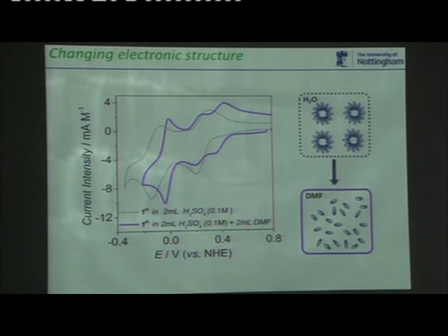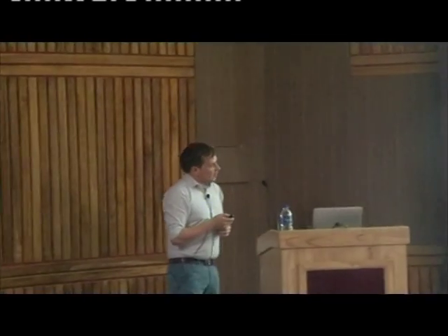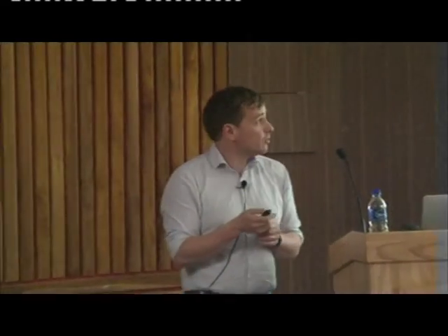And what this means is that these POM aggregates are having a major influence. The electronic structure is changing through the formation of the aggregates, and we think it's through Coulombic repulsion, i.e. when we have the micelles, it's more difficult to add electrons to them through repulsions. So we're having a look, and we'll try to get to the bottom of it soon. So yeah, just to summarize, that's the areas in which we work.